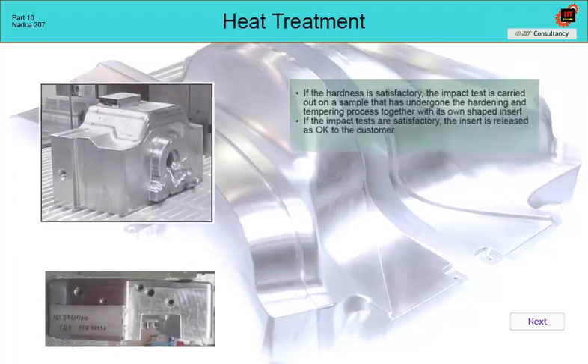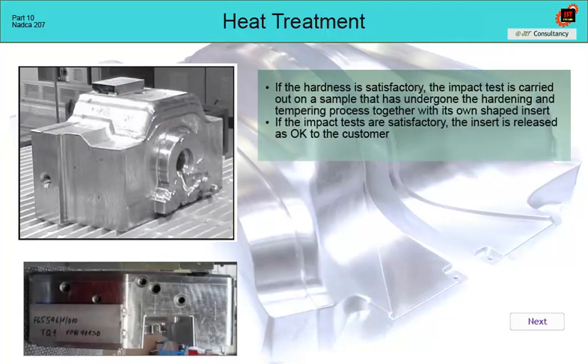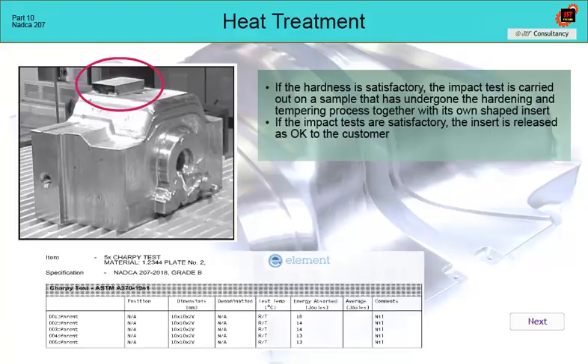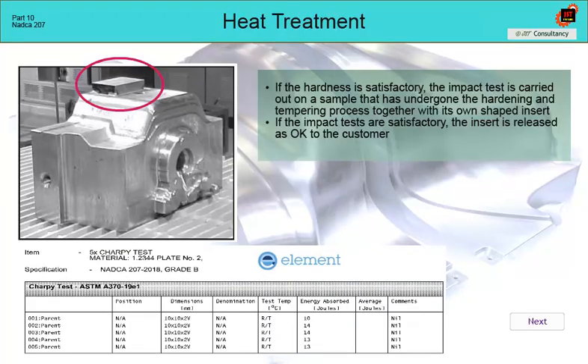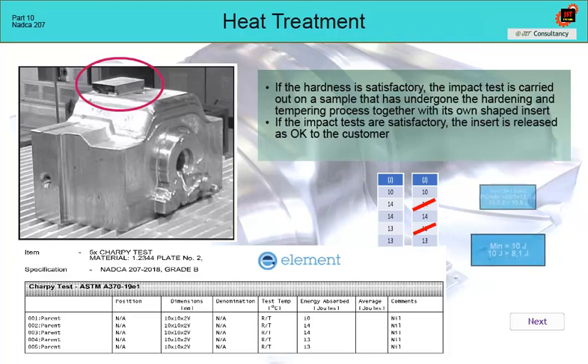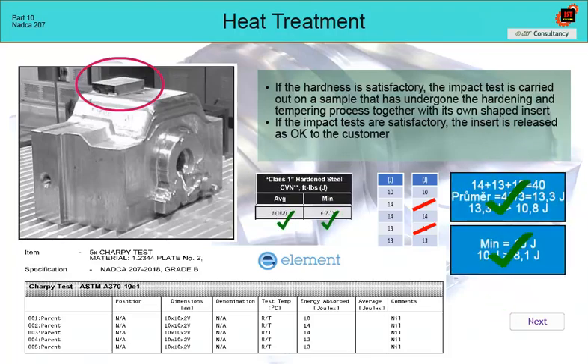In the next step, it is necessary to verify the quality of the heat treatment by impact tests according to the Nadca 207 specification. The figure shows how the test coupon is attached to the die for the hardening process. This coupon is separated from the die and sent for testing to a certified laboratory, for example, Element Materials Technology. The laboratory itself produces samples for impact tests and performs tests with the declared result. All this within 48 hours. If the impact test results are okay within the specification, the insert is released for the customer.